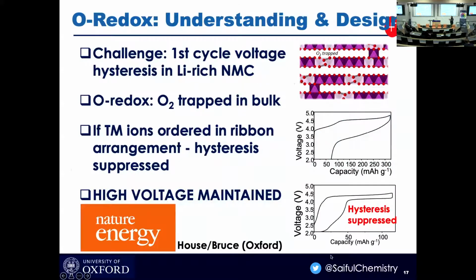So I'll just show one results slide, and this is really lovely work from somebody in the audience, Rob House, and Peter Bruce's group. They looked at trying to understand the problems within the lithium-rich layered oxide. They do present challenges. There's capacity fade, which means on cycling they lose energy capacity, and there's a voltage loss. The voltage loss is shown in that curve in the middle. Voltage against capacity, the top line is on charging, and the bottom line is on discharging. You can see there's a voltage loss. So we want to understand what's going on.